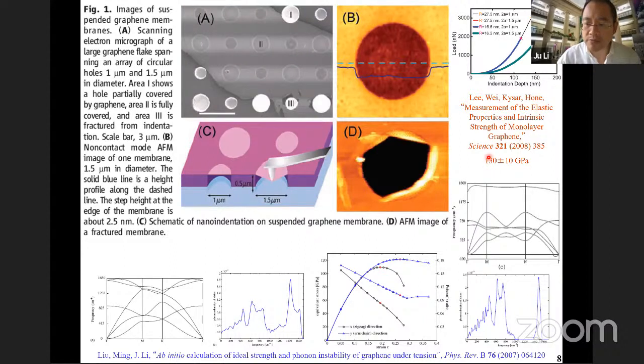In the experiment by Columbia University, they used an AFM tip whose tip radius is from 16 to 27 nanometers, and they poked on this monolayer membrane, which is 1 or 1.5 microns. And they found out two things. Number one, to fit the load-displacement curve, they needed a nonlinear constitutive relation. And number two, at the point where it breaks, the stress right beneath the indenter is on the order of 130 gigapascal. That means that right before the graphene breaks, it's fundamentally a different material from stress-free graphene, because many physical properties like thermal conductivity, electrical conductivity, and superconductivity depend on the electronic and phonon band structures, and they really change under stress.